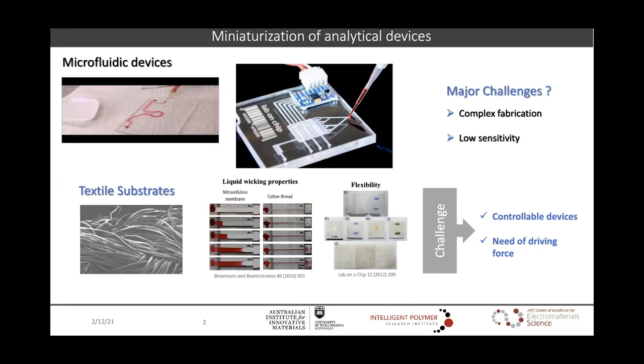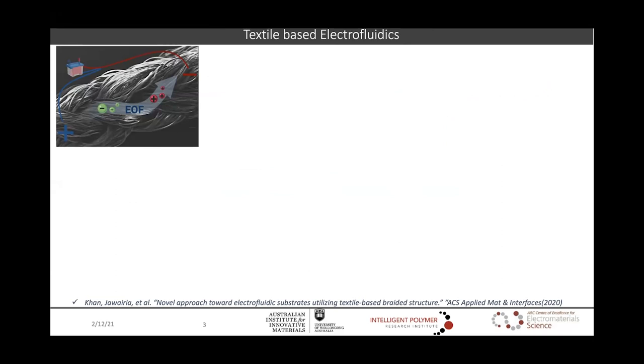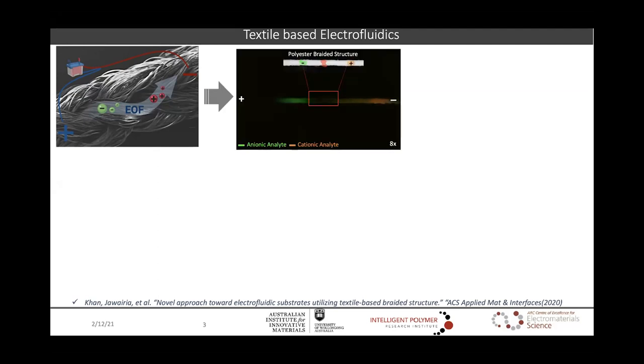However, to obtain controllable devices and precise fluid control, a driving force other than simple wicking action is required. So here we explored a groundbreaking new approach where we used an electric field for precise fluid control and the migration of solutes on the surface of fiber constructs. The fluid held as a surface layer within the fiber capillaries generates both EOF and solute electrophoretic migration in a controlled manner on application of an electric field, and as a result, charged analytes separate electrophoretically based on their charge to size ratio. More significantly, with close environmental controls and proper surface modifications, it becomes possible to mimic separations formerly achievable within capillaries on this open, surface accessible system.